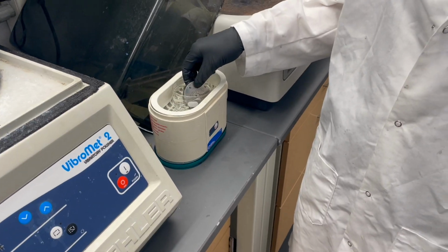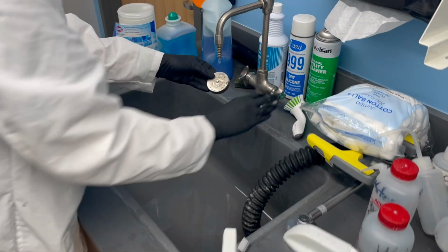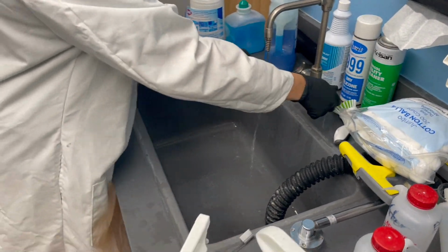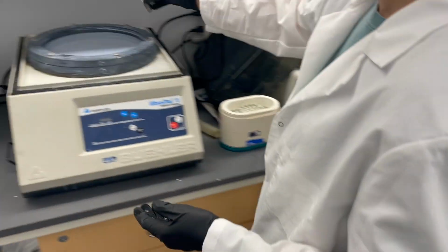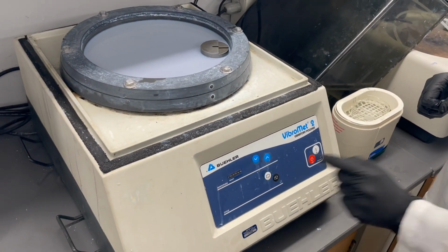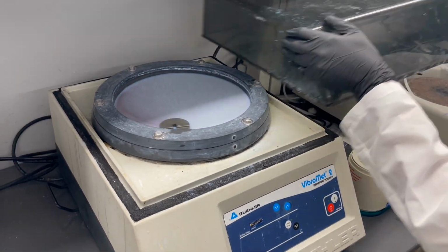When the ultrasonic cleaning cycle is finished, take the polishing fixture and rinse it with water. Place it face down in the vibratory polisher. Turn on the polisher, press the white oscillate button, and set the amplitude to 20%.